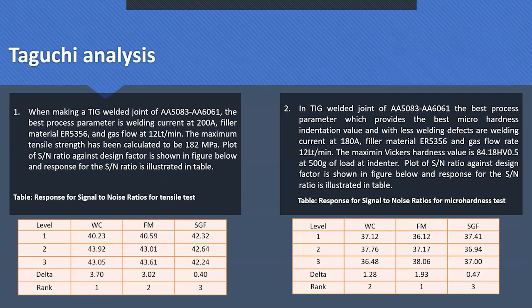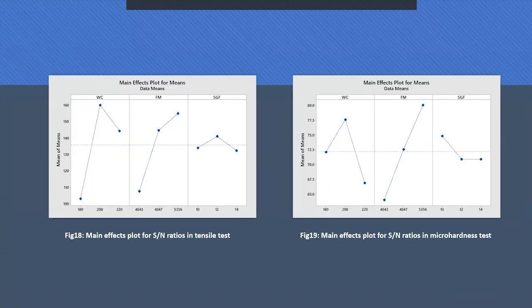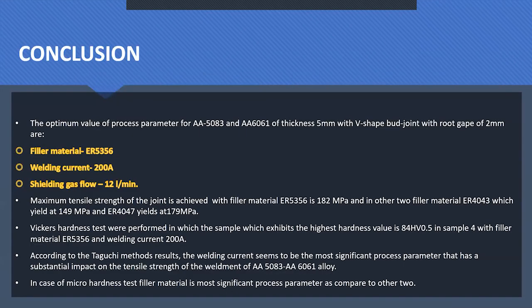Now coming to Taguchi analysis. Taguchi analysis has been done on both tensile testing and micro hardness tests. In the case of the tensile test, the most dominating factor is welding current, which has rank 1, followed by filler material, and lastly shielding gas flow. In the case of the micro hardness test, the main dominating factor is filler material, followed by welding current, and lastly shielding gas flow. These are the mean SN curves for both the tensile test and micro hardness, for the higher-is-better Taguchi design. The optimum values for tensile testing are welding current 200 ampere, filler material 5356, and shielding gas flow 12 liters per minute. In micro hardness, the optimum values are welding current 200 ampere, filler material 5356, and shielding gas flow 10 liters per minute.